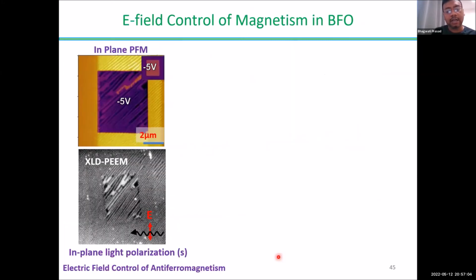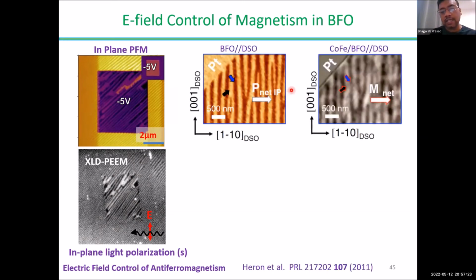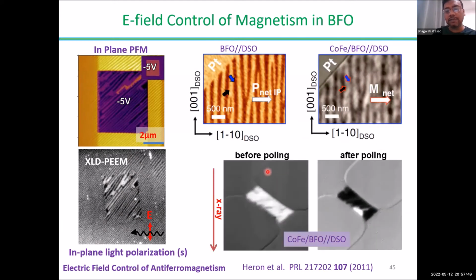People in the past, our group with Ramesh, have demonstrated that if you switch the ferroelectric polarization or ferroelectric domains in these materials, the antiferromagnetic domains also switch. So there is a one-to-one correlation between the antiferromagnetic domain and the ferroelectric domain, and in fact that was well established by putting the ferromagnet cobalt iron on top of the BFO, where there is a one-to-one correlation between the ferroelectric domain of the BFO and the ferromagnetic domain of the cobalt iron. That means there is a strong interaction between the canted moment of the BFO and the magnetic moments of the cobalt iron, and you can switch them back and forth with the electric field. This is before poling and this is after poling. This was all done at higher voltage, 500 volt, 5 volt.